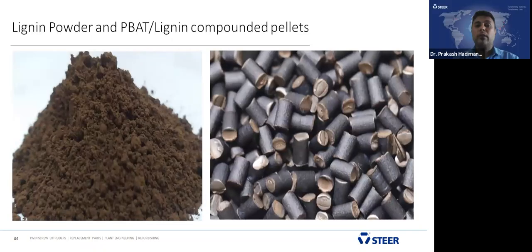Now we move to the lignin and PBAT category, and later we'll cover wood powder and PBAT. Interestingly, this PBAT is recycled again, and lignin is a virgin powder. We compounded PBAT with the lignin, and these are the pellets. The pellets were very good, with a smooth surface, no voids, and glossy. We also observed an improvement in the mechanical properties of this product.